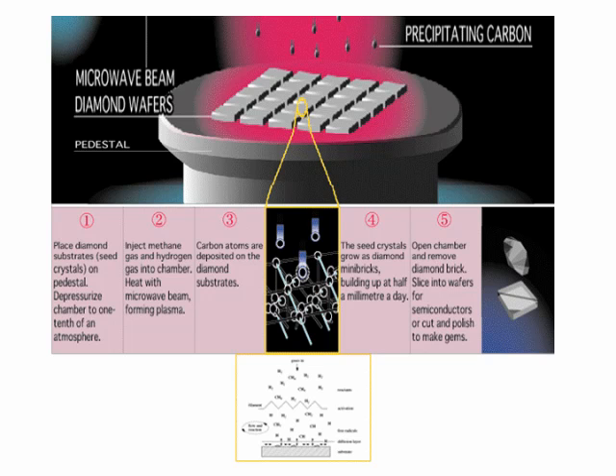Instead of going to high pressure, I go the other direction. Actually make it a vacuum chamber, right? And then I flood that vacuum chamber with methane gas. It has carbon in it. I'm going to break the bond between the carbon and the hydrogen in the methane gas. And then I'm going to heat the substrate down here, and I'm going to deposit the carbon atoms directly on the diamond. We'll blow this diagram up in just a second.